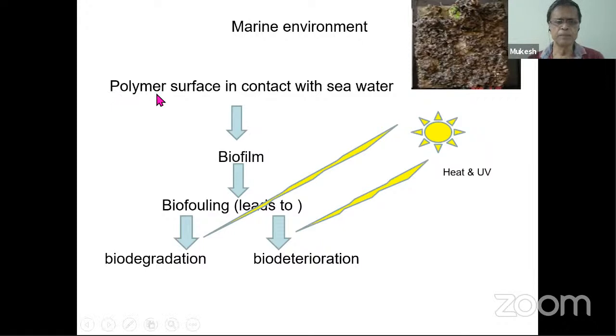Initially, as the polymer surface comes into contact with seawater, there is something called biofilm formation. That means bacteria get attached. The different types of bacteria present in the marine environment get attached to the surface of the polymer, depending upon the surface properties. Surface properties could be surface energy, roughness, and so on. Once these microorganisms attach, larger organisms start attaching, which is called biofouling, like shells, polychaetes, barnacles. They are much larger organisms, and they attach to these surfaces.